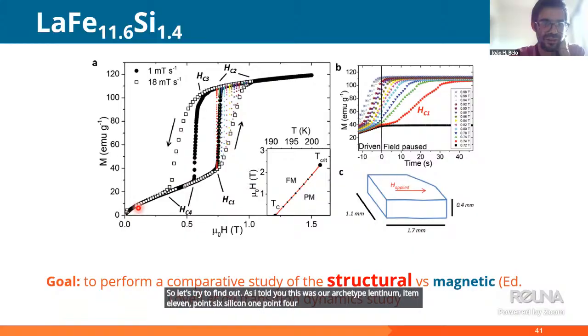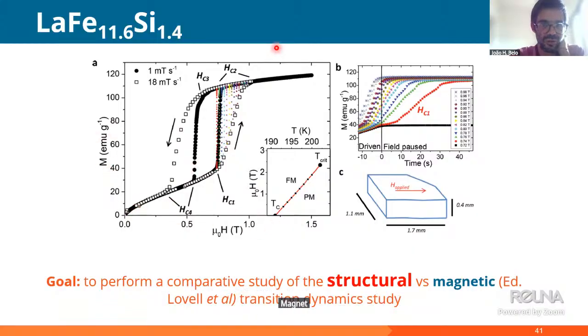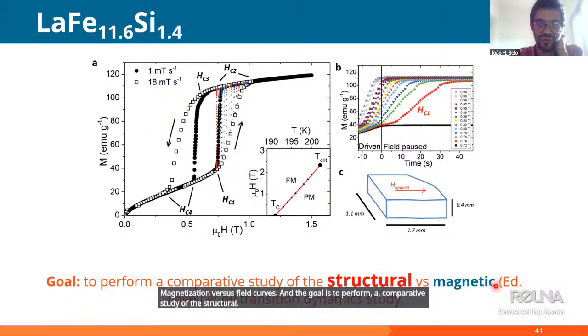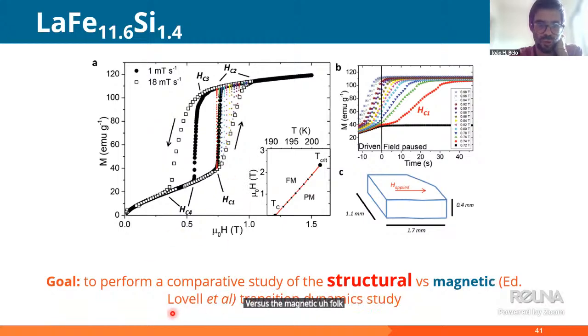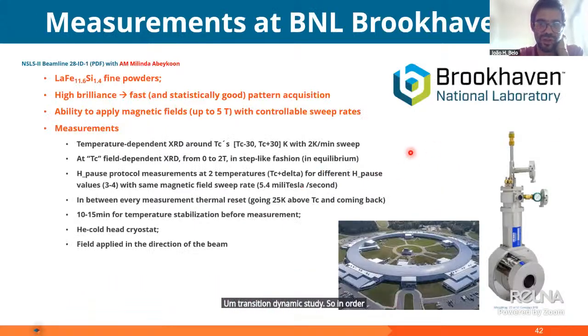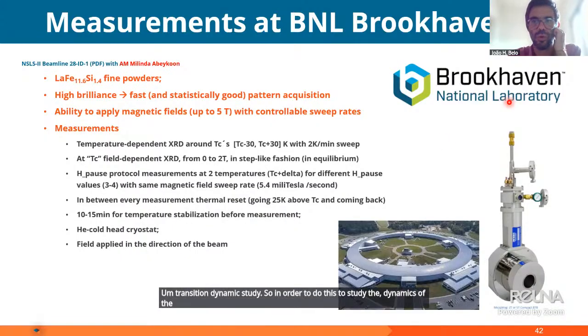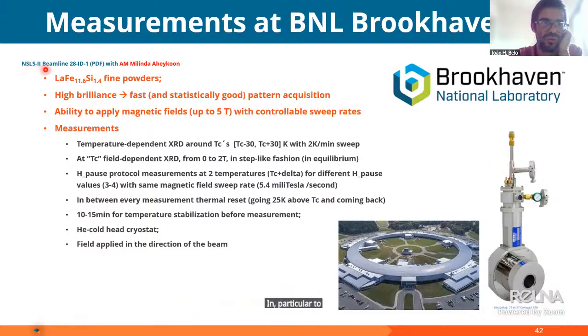As I told you, this was our archetype, lanthanum iron 11.6, silicon 1.4. It presents these very beautiful magnetization versus field curves. And the goal is to perform a comparative study of the structural versus the magnetic transition dynamics, which was the focus of Edmund Lovell's work. In order to study the dynamics of the lattice, we went to Brookhaven National Laboratory in the US, in particular to the NSLS-2 synchrotron with this beamline, where the beamline scientist is Milinda Abeykoon, a very brilliant beamline scientist.